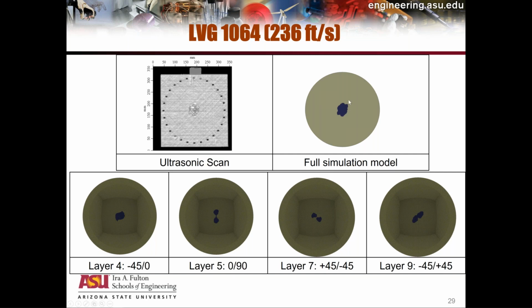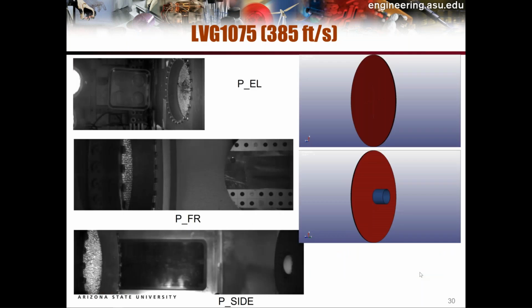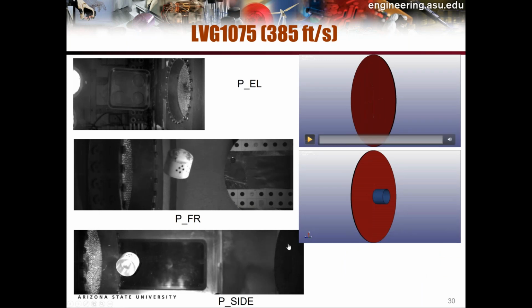So when you look at the full simulation model, this is the area where we do see delamination in the model. This compares reasonably well with what we see with the ultrasonic scan. Ultrasonic scan will not tell us where the actual delamination is, but we can get that information from the computer model. For example, layer 4 shows this is the region where we have delamination, layer 5, layer 7, layer 9, and so on. So we have more fidelity available in the computer model that's not available in the experimental result. So this is an impact at a much higher test where there's considerable damage, but the projectile is still contained. And here are the computer predictions.